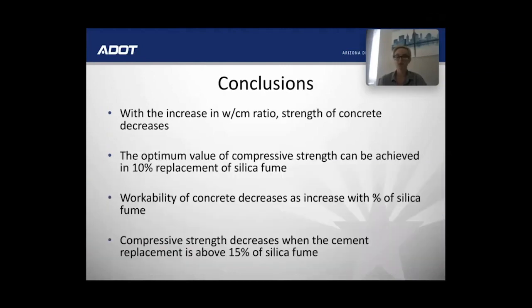From the results, it is concluded that silica fume is a better replacement of cement. The rate of strength gain in silica fume concrete is very high, and after performing all the tests and analyzing their results, the following conclusions can be derived. With the increase in water-cement ratio, strength of concrete decreases. The optimum value of compressive strength can be achieved at 10% replacement of silica fume. Workability of concrete decreases as the percent of silica fume increases. And compressive strength decreases when the cement replacement is above 15% of silica fume.